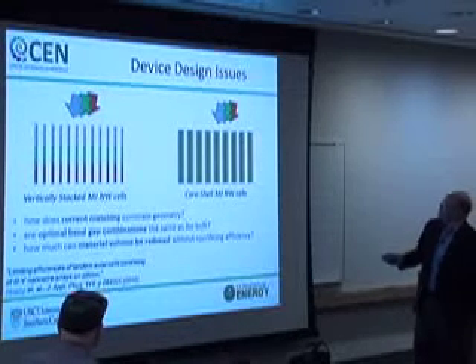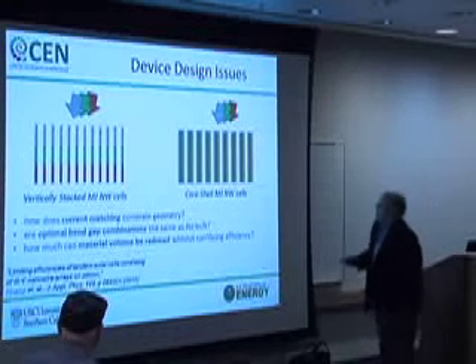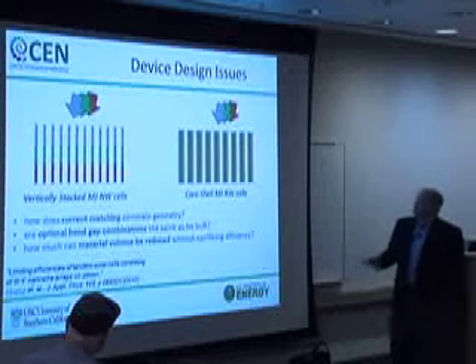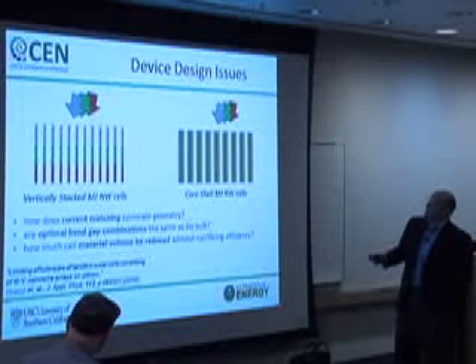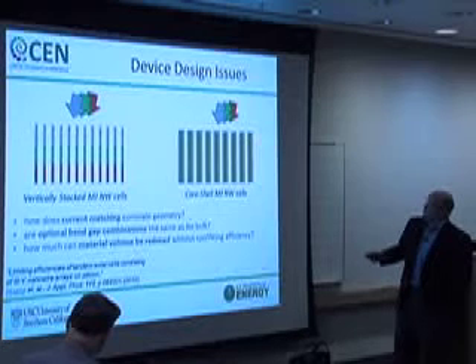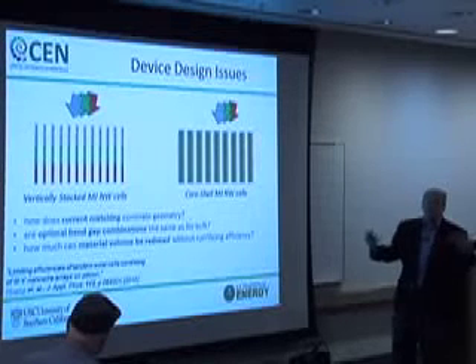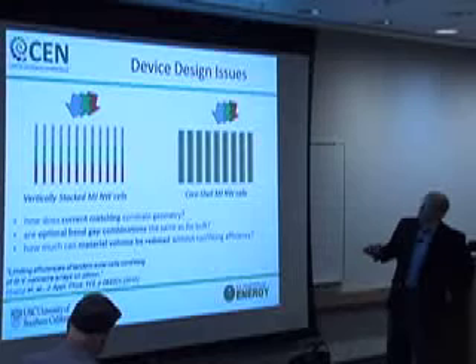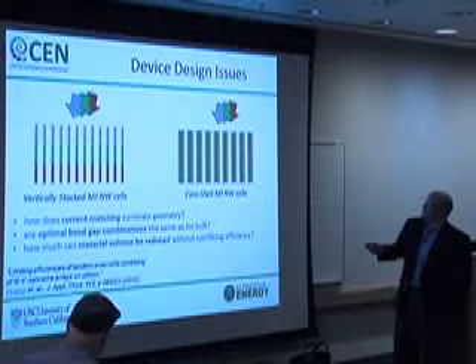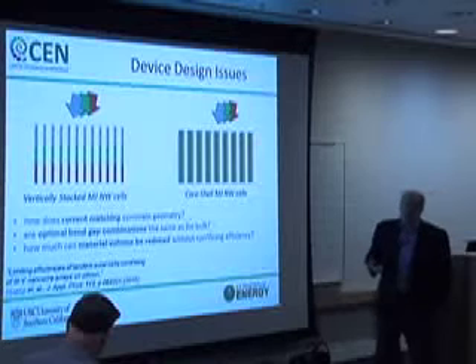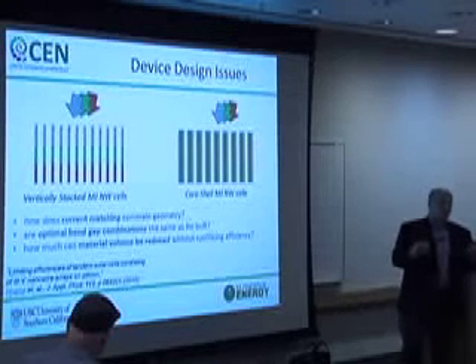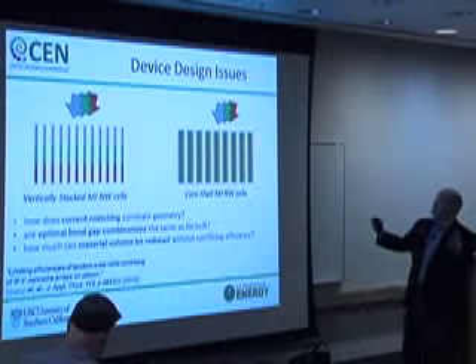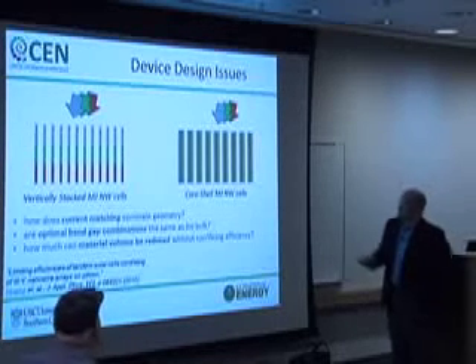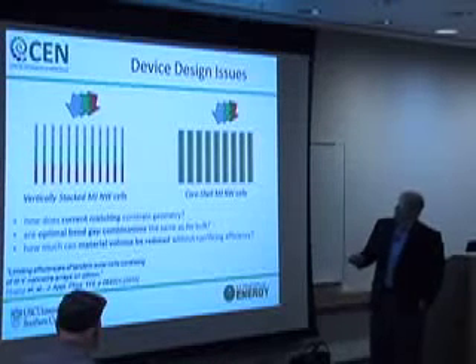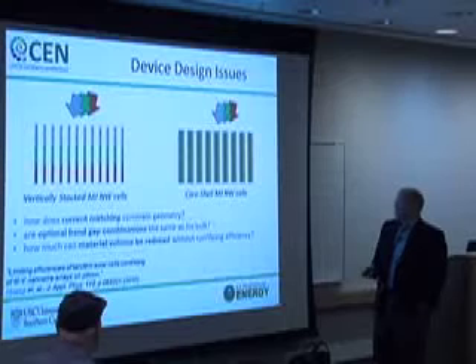We could also think about using a core shell kind of a structure. It turns out that that's not very practical because, for one thing, light of all colors will be incident on all of the materials. You don't get the spectral separation that you're hoping to achieve with a tandem cell, for one thing. And secondly, the thickness of these layers in order to absorb the light above their band gaps would have to be substantial. And all of a sudden these things are no longer wires, they become just chunks of material. And so we're focusing on trying to accomplish this thing.